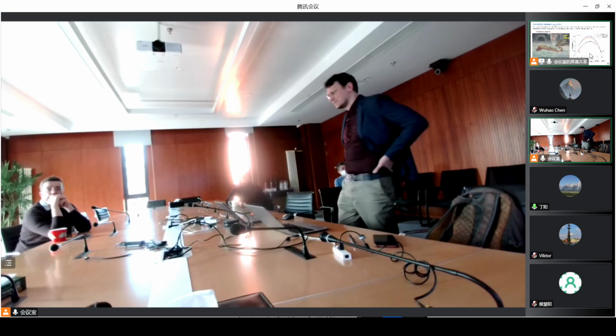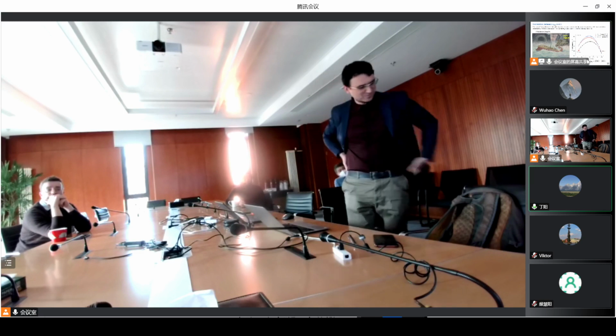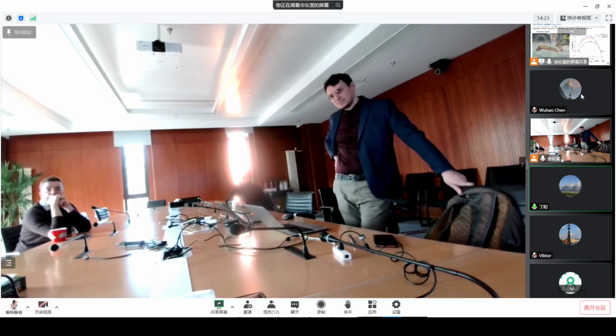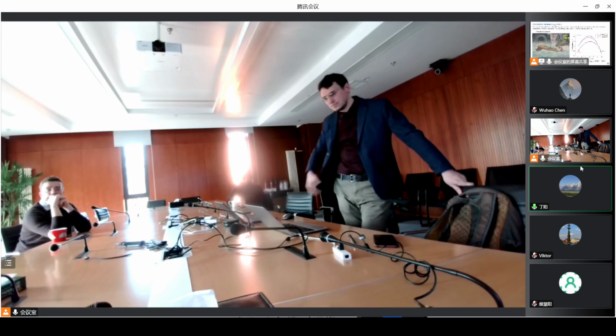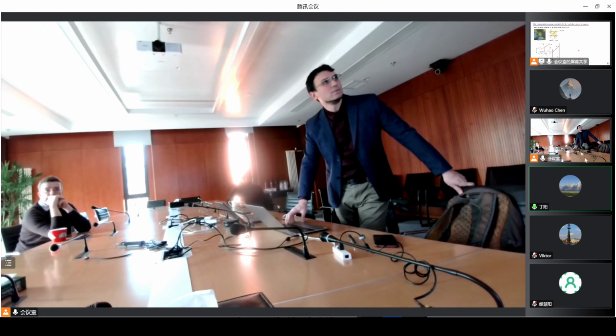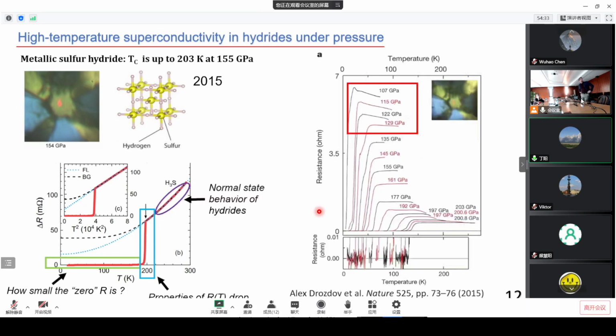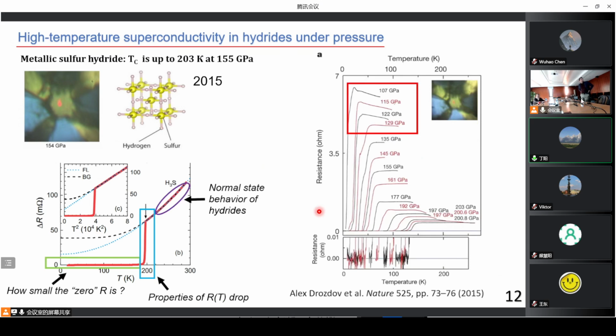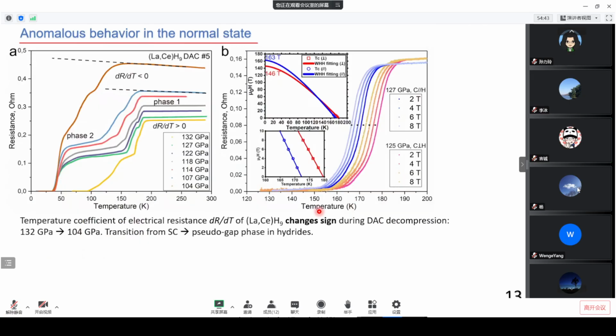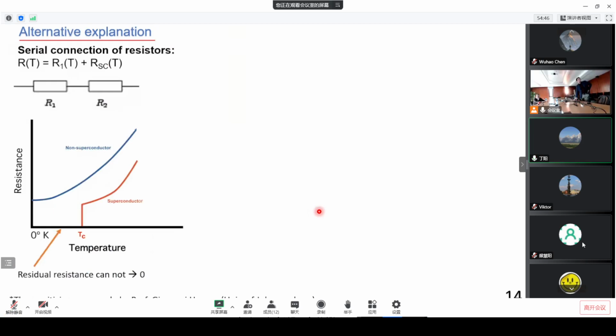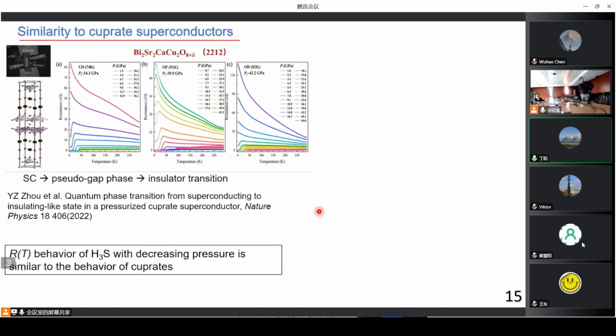Okay, I have a question for you. It's very interesting that you raised the question about the strange-metal resistivity behavior just above TC. You found a linear relationship between the temperature and the resistance. This is also already a very famous question in cuprates, where there is a strange metal region. On the other hand, you mentioned that TC is very strongly dependent on the electron-phonon coupling. This seems a little bit of a dilemma, because BCS theory is not suitable for high-temperature cuprate superconductors. So what's your opinion?